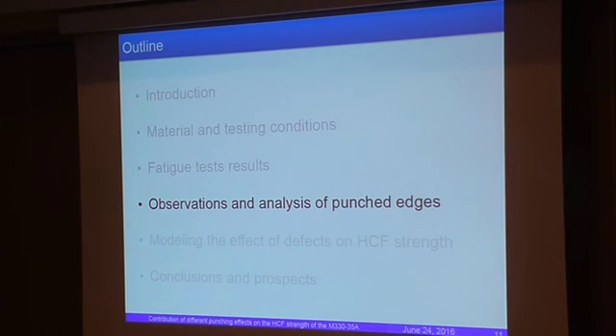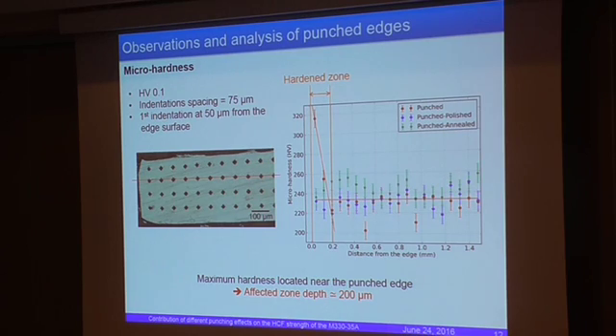So now I will explain how we quantified these three effects, namely hardening, residual stresses, and geometrical defects. First we made micro-hardness measurements. As you can see here, we find hardening in about a 200 microns layer close to the edge, just in the case of punched specimens. If you polish or anneal your specimens, you don't get any hardening anymore. But as you can see, the resolution is pretty low here, so you don't really have the slope and the exact evolution of the micro-hardness very close to the edge.